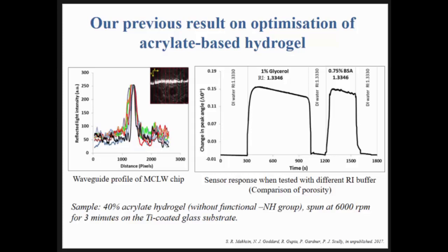We set the refractive index of this buffer at the same value. So if there is a change at the same sensitivity, happening at the same layer on the waveguide layer, it will cause the same change in the peak angle here. So it indicates to us that the porosity is good enough, whereby we allow the analyte to diffuse in at the same point.